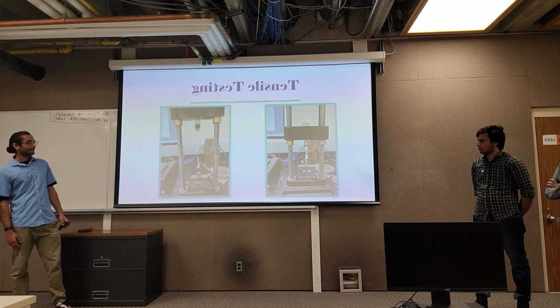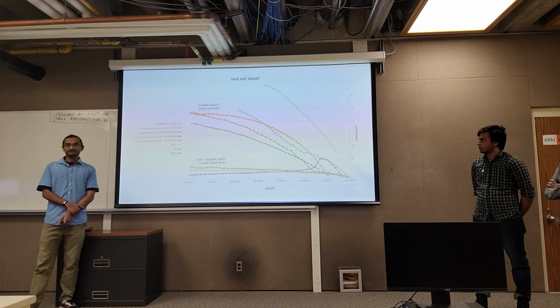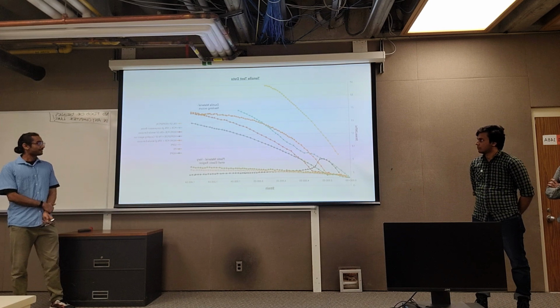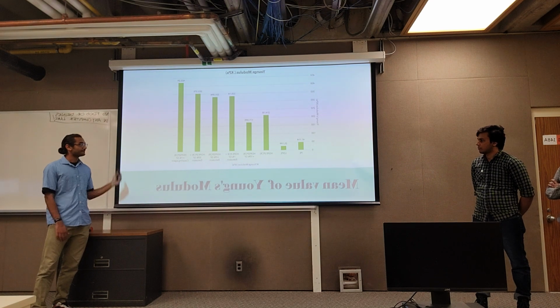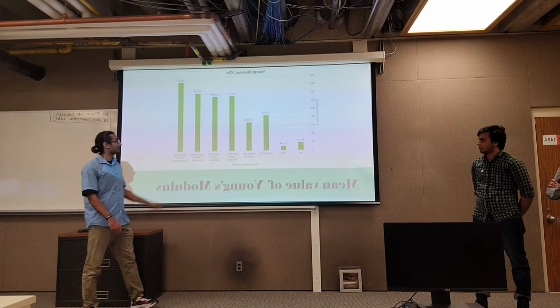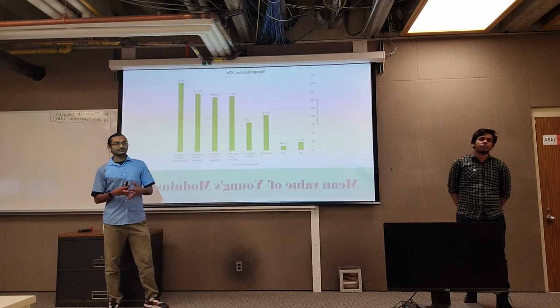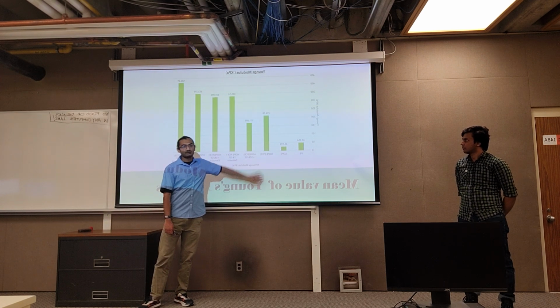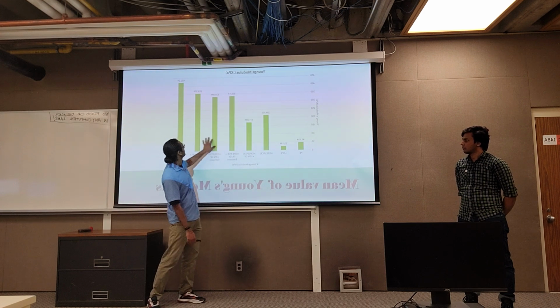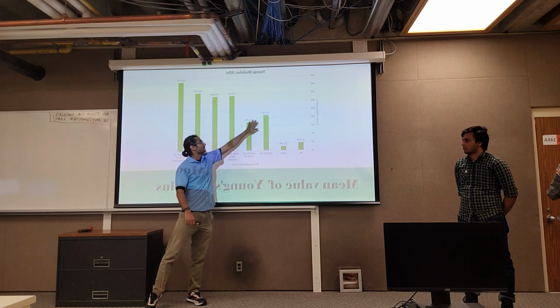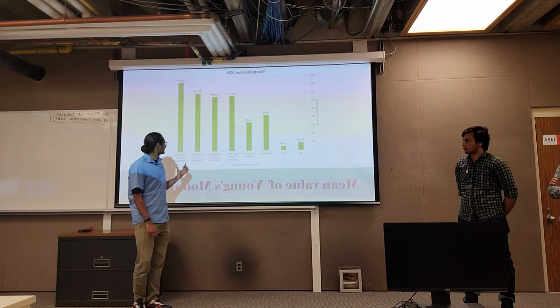Moving on to the tensile test results. These are the compiled test results of the tensile test we had done. Here also, through the Young's modulus, we were able to see that the extrusion way was quite better and consistent in increasing the strength of the PCR rather than going with the compression one. So this is the bare HDPE. By the addition of reinforcement, there was an increment in the results for the extrusion, and for the compression ones, there was a decrement. But for the coupling agent, we'll talk about this graph as well.